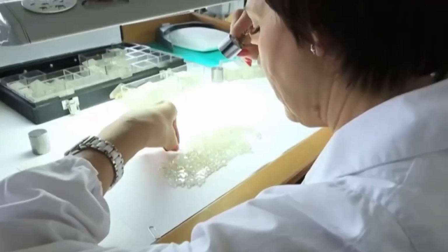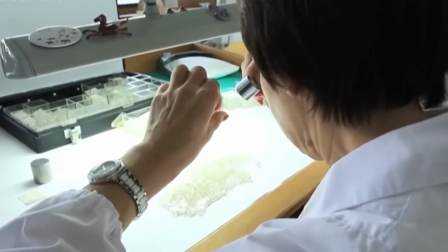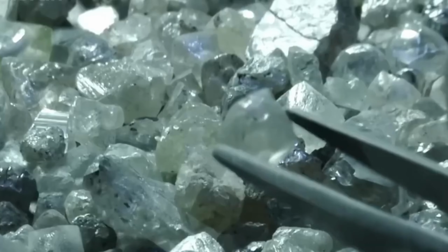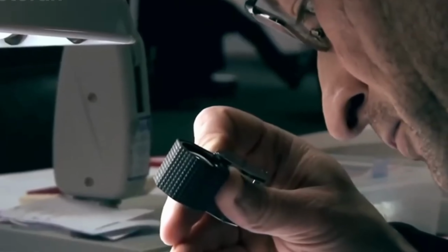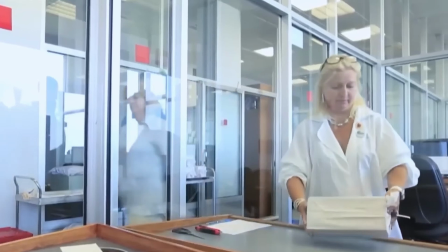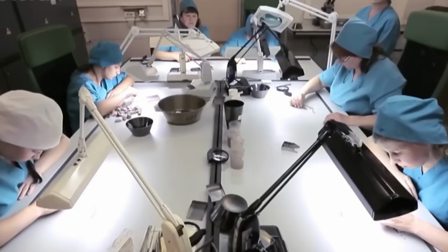Graders inspect the stone under 10 times magnification to identify inclusions, surface blemishes, growth patterns, and any metallic remnants from the growth process. Lab-grown diamonds often show unique internal features. CVD stones may reveal striations from layer-by-layer growth, while HPHT stones can show metallic flux inclusions. These are natural characteristics of the creation process and do not necessarily affect appearance.